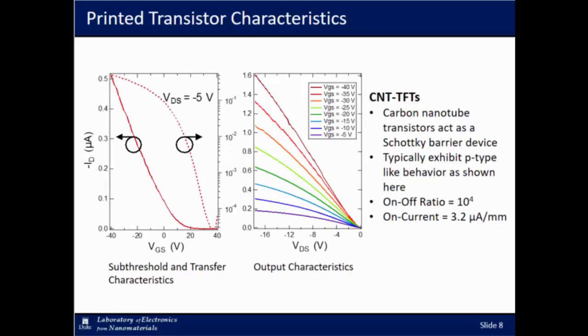So carbon nanotube transistors, they're Schottky barrier devices, so they're not intrinsically doped N or P-type. It's an intrinsic channel where the behavior is determined by the work function of the metal contacts. And so these show P-type behavior, which is pretty typical for carbon nanotube transistors. It's a little more difficult to get N-type behavior. And they have an on-off ratio of 10 to the 4 and an on current of 3.2 microamps per millimeter, which is about average for printed nanomaterial transistors.